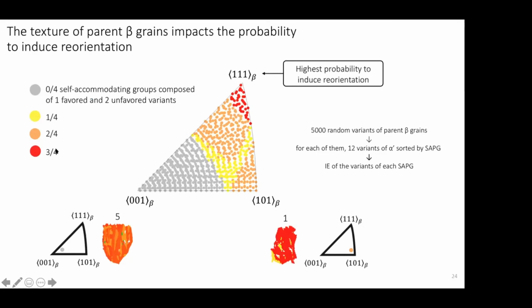And experimentally, in practice, what is the consequence? The consequence is that we have a strong link between the orientation of the parent beta grain, so the texture of the parent beta grain, and the fact that you can induce reorientation or not. For example, if you have a texture close to 100, you cannot create self-accommodating groups that can induce a complete reorientation. And experimentally that was the case, because in grain 5 we couldn't see complete reorientation, but it was just because it wasn't possible. By contrast, if you have a texture close to 111, you have a high probability to create self-accommodating groups that will respect the criterion to induce a complete reorientation. And close to 101, we were in the case of grain 1. We have a quite high probability to induce complete reorientation, and that happened.